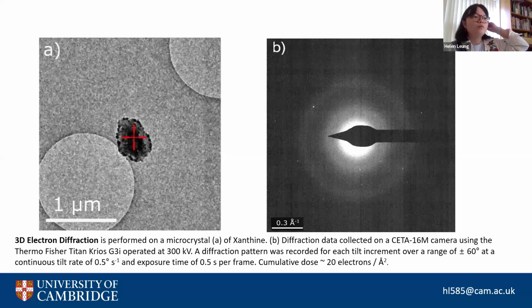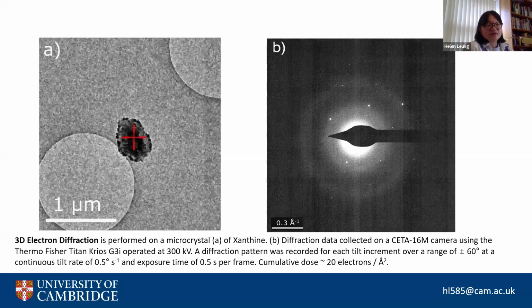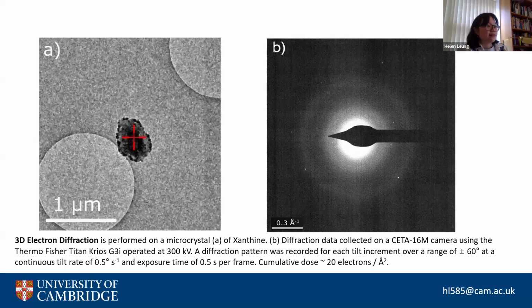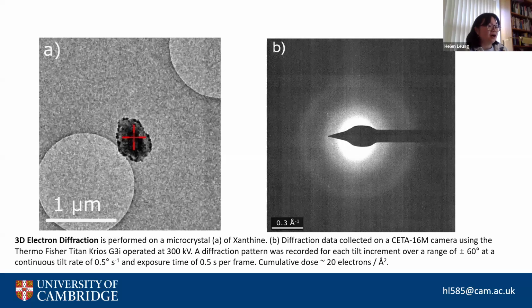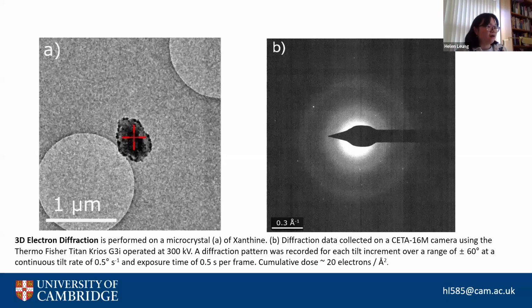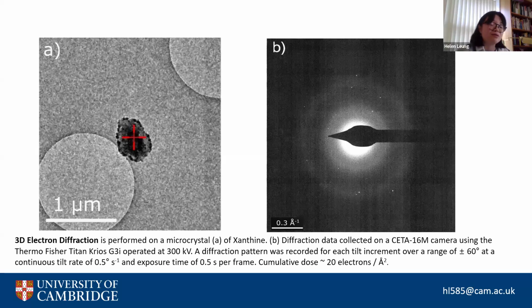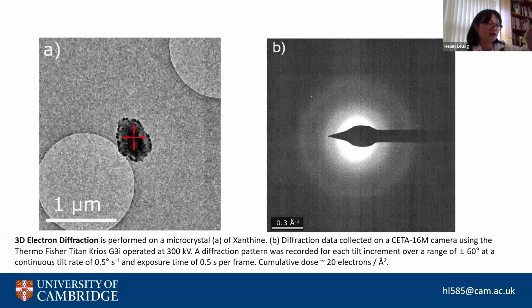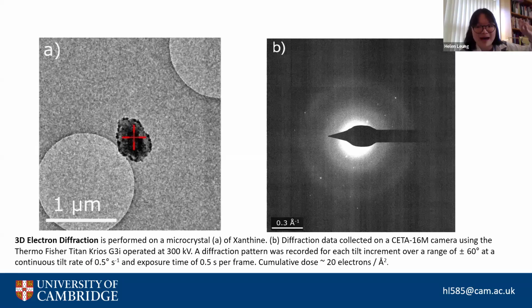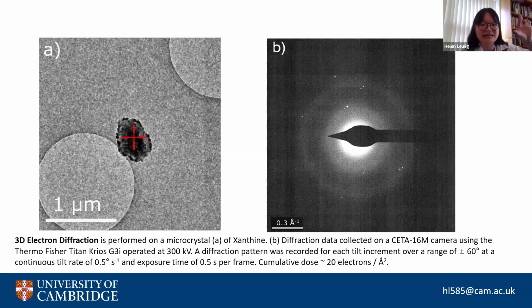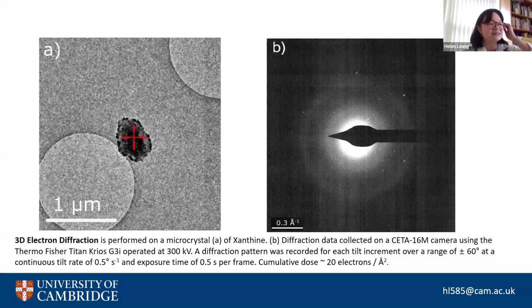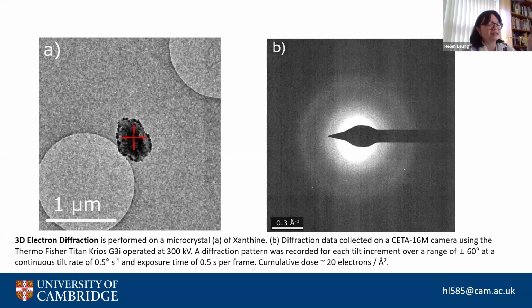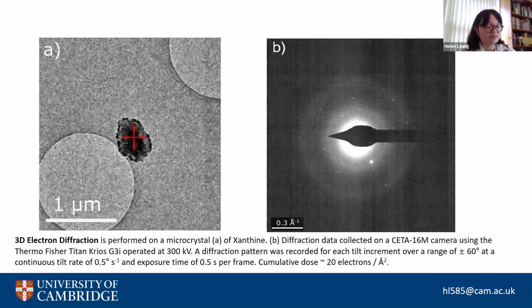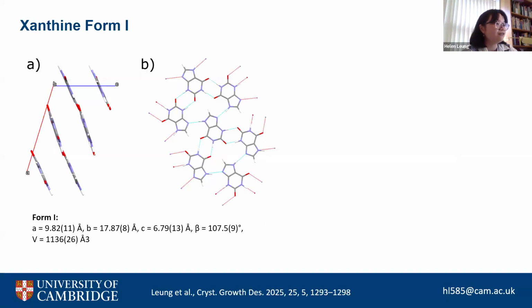So we ended up collecting a successful data set from xanthine, from a crystal which is under a micron in size. You can see here on the panel on the left, I would estimate maybe 300 nanometers. There's some amorphous contamination on top of it, so you have to look quite carefully, but underneath that there is a much clearer, darker shape, which is our crystal. And we collected this data in the same conditions as with the indomethacin. And from this, we achieved a structure solution.